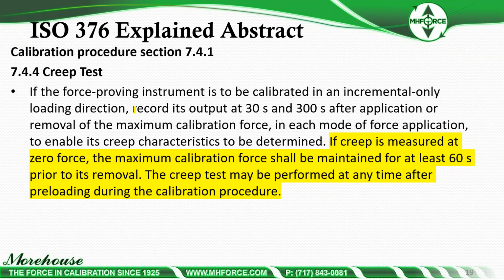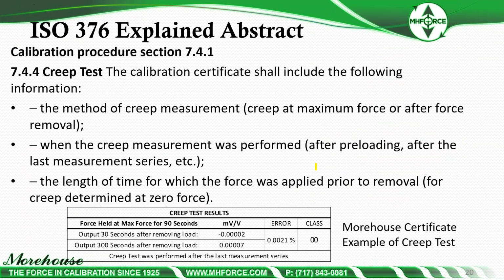And to do the creep test, we're going to record its output at 30 seconds and basically 5 minutes, 300 seconds after application or removal of the maximum calibration force. In each mode of force application, to enable its creep characteristics to be determined, if creep is to be measured at 0 force, the maximum calibration force shall be maintained for at least 60 seconds prior to its removal. The creep test may be performed at any time after preloading during the calibration procedure. So we're going to get into that. It's a lot to process right now. We're going to get into that in a little more detail.